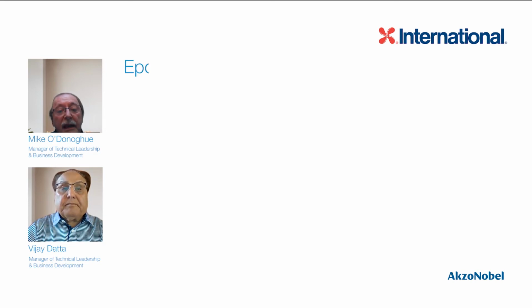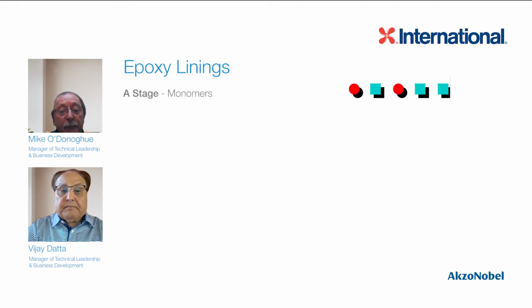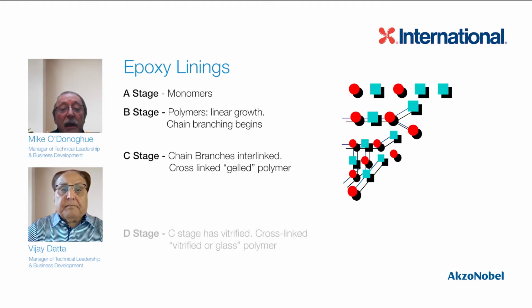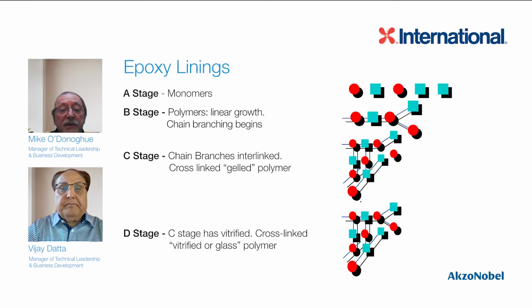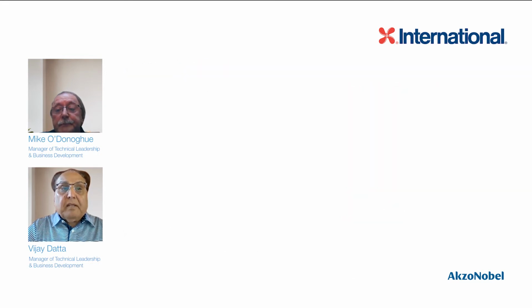When it comes to epoxy linings, there's a very simple scheme of things. If we look at the four stages, the A, B, C, and D stages of epoxy linings, we start with the monomers and we react them together. And the polymers are formed with linear growth. Then they branch out and ultimately set into a D stage, the final stage, where you have a vitrified gel and you have your polymer fully formed epoxy lining, which is a coating system that is used widely in the oil patch. Now, look at the different epoxy resins, Mike, that we use here.